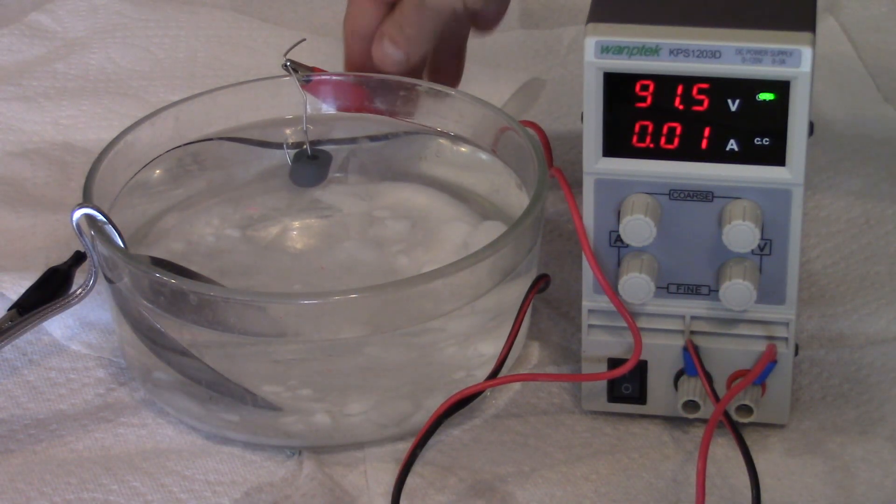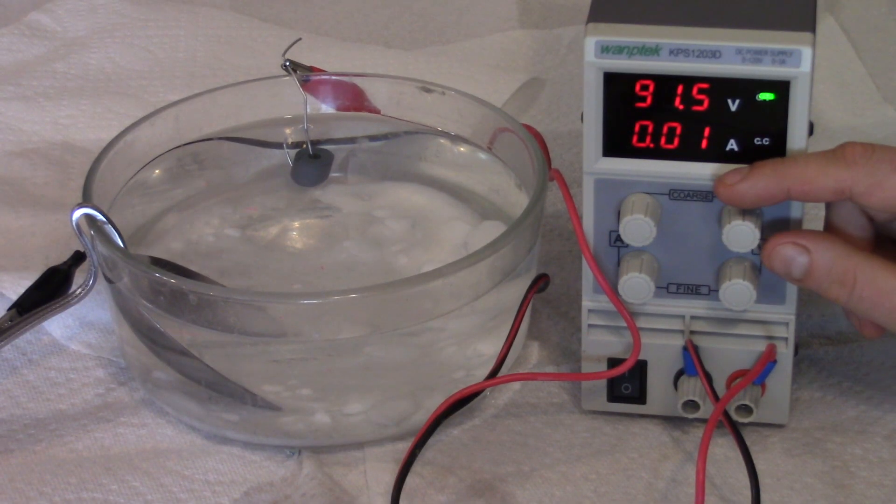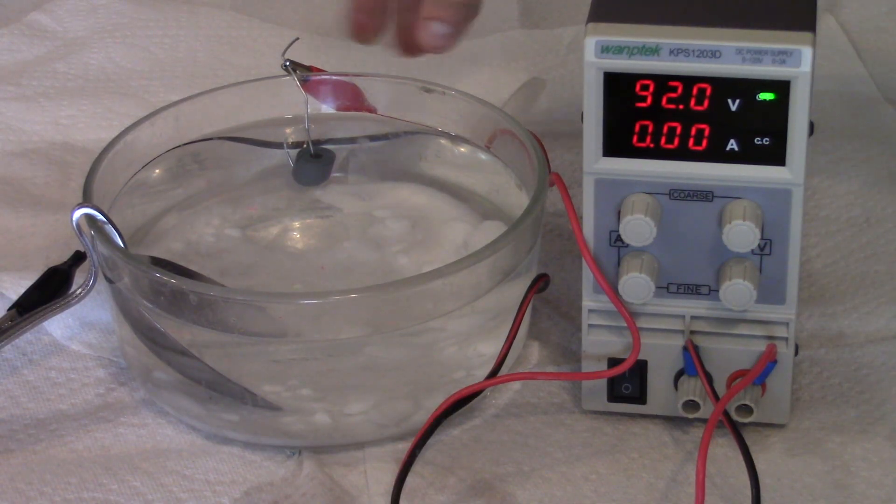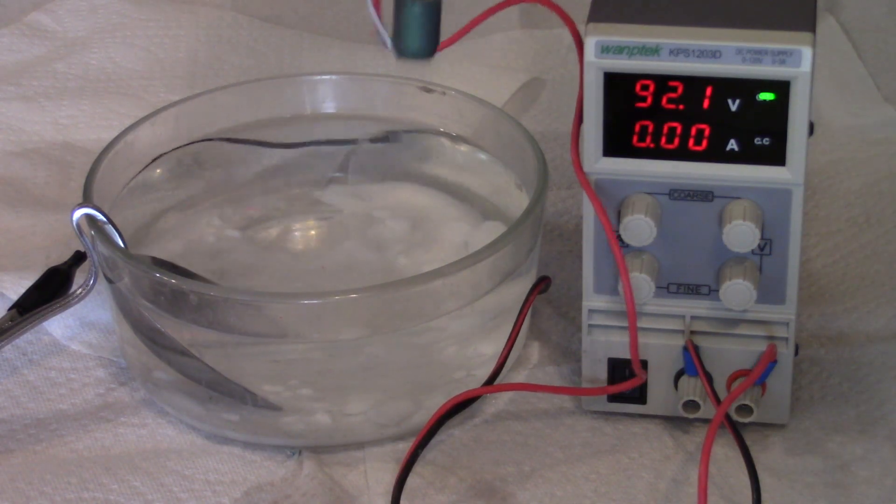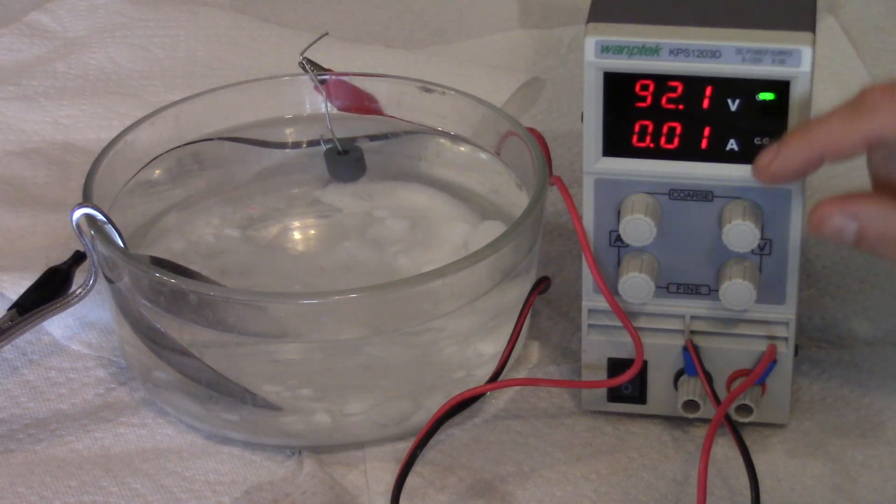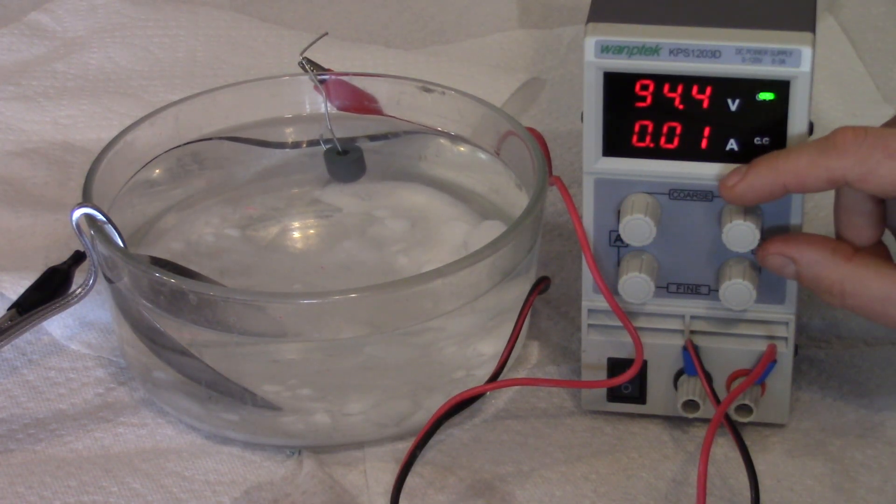So if you want like teal or turquoise it's a very slight difference between the two, so you got to be really sensitive, you got to be really careful and take it slow. At 92, let's get more green in the teal color, very cool color there. At 94 you're starting to get darker and darker green now.